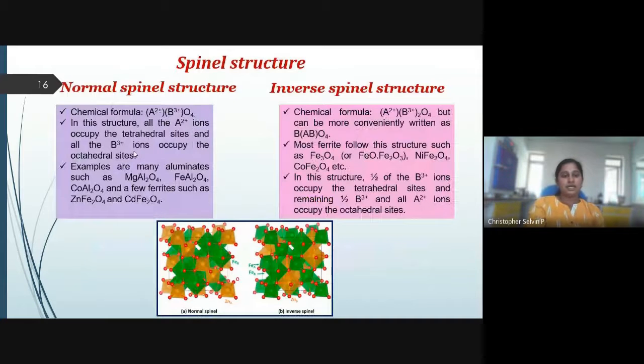As mentioned earlier, we have two different spinel structures: normal and inverse spinel structure. The key difference is that in the normal spinel, A site ions occupy the tetrahedral sites and all the B site ions occupy the octahedral sites. Whereas in the case of inverse spinel structure, half of the B site ions occupy tetrahedral sites, while the remaining half of the B site ions and the A site ions occupy the octahedral sites. So this imposes the difference in the spinel structure.